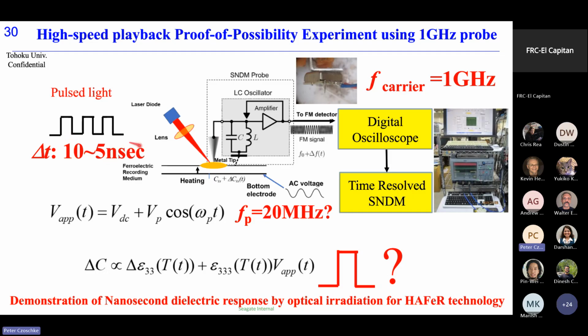If we reduce the pulse duration down to 5 nanoseconds, what happens? Alternating voltage application is meaningless, but the DC voltage can be applied. So if we apply the DC bias voltage, and if the nonlinear constant increases, we can detect this term as a linear dielectric response.